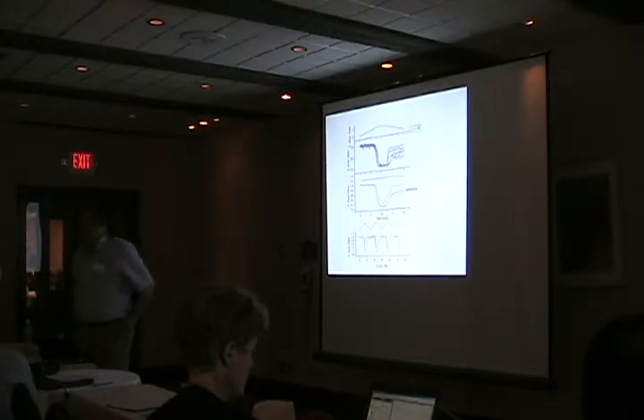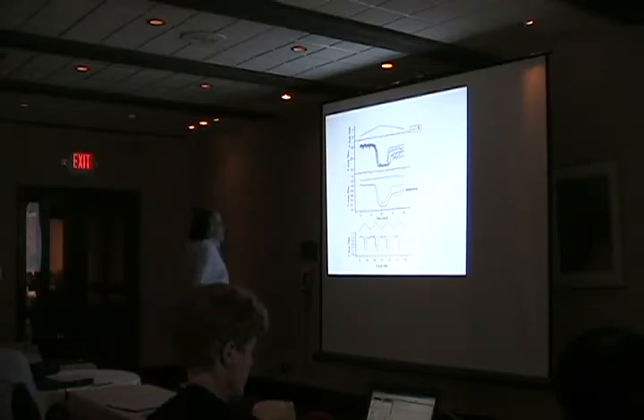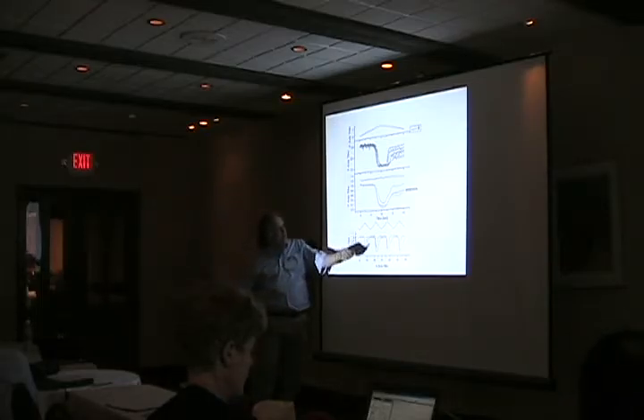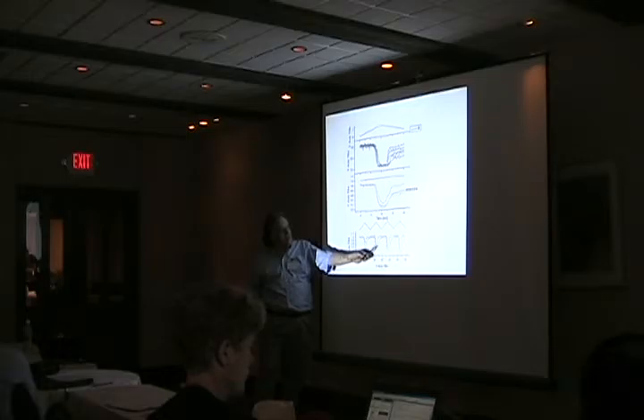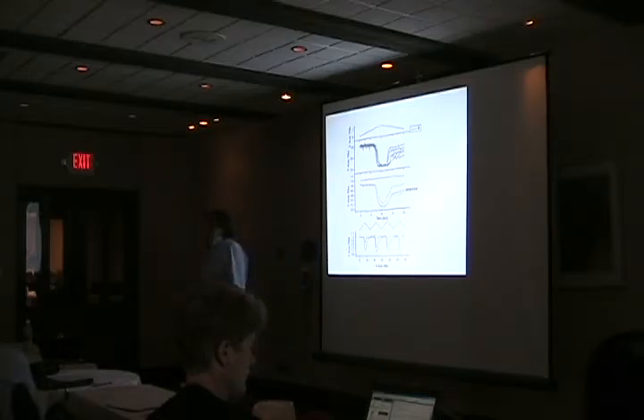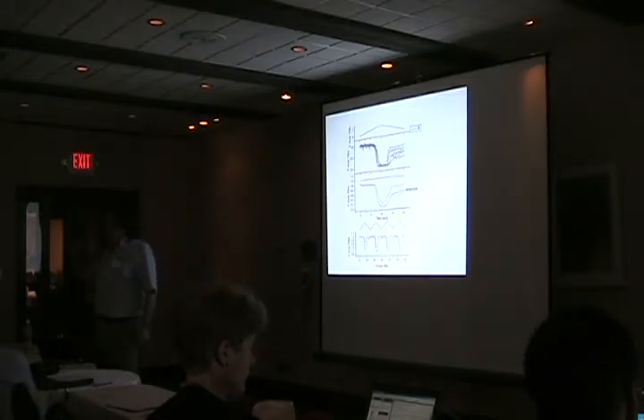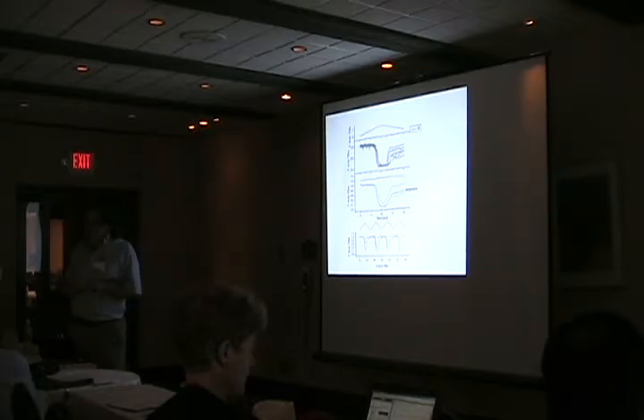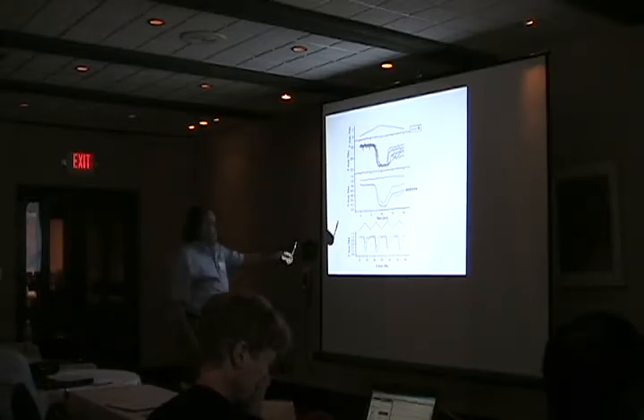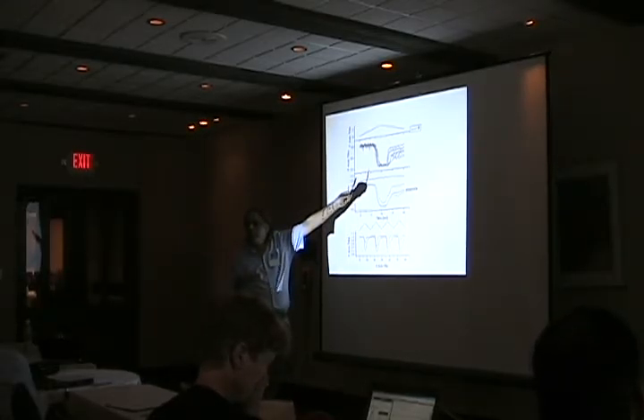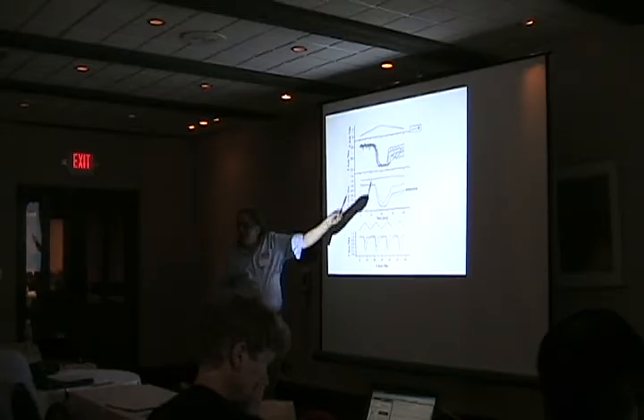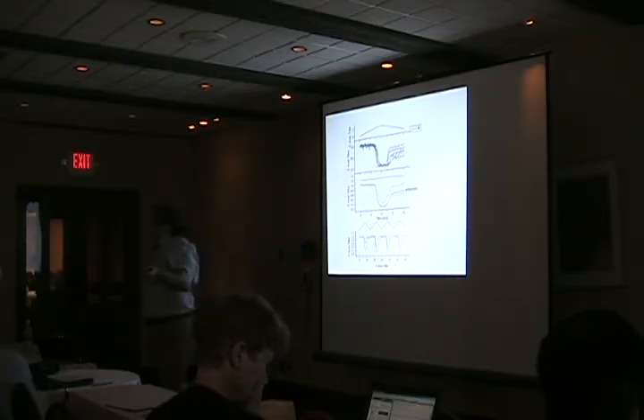These are some experiments, and one of the things that came out of this is if we cycle the potential very rapidly, we reversibly oxidize and reduce aggregates, just sitting there oxidizing it, taking the charges out. But if you do it more slowly and let the positive charges stay in the particles for a while, it becomes very difficult to remove the charges. Very irreversible.